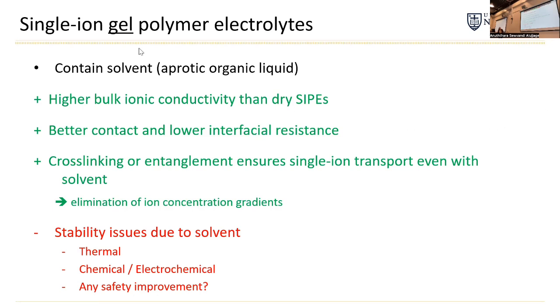If we add solvent, we're definitely getting higher bulk ionic conductivity, but there are other benefits as well. The plastic is softer, so that gives better contact with electrodes and in general lower interfacial resistance because of that improved contact. We can still make the system single ion conducting, with no anion motion, as long as the polymer, when it's swelled in the liquid, is cross-linked or somehow entangled so that the polymer chains can't really translate. And so we still eliminate the ion concentration gradients, which is good.